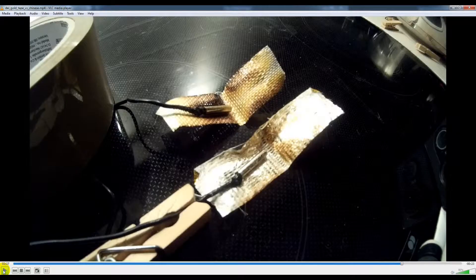So that was the test. What can we take from this? For sure, the DEI gold tape can handle much higher temperatures — the structure stayed intact and there was no noticeable gassing or smoking. Is it worth the money? It depends on where you're using the tapes. If you're going to use it in an area that gets up to around 100°C max, both tapes will remain intact and offer some protection. But getting up to extreme temperatures — I'm guessing 200 to 250°C — the unbranded Chinese tape starts to break down, gets holes in it, and becomes completely useless, whereas the DEI gold tape maintains its structure.